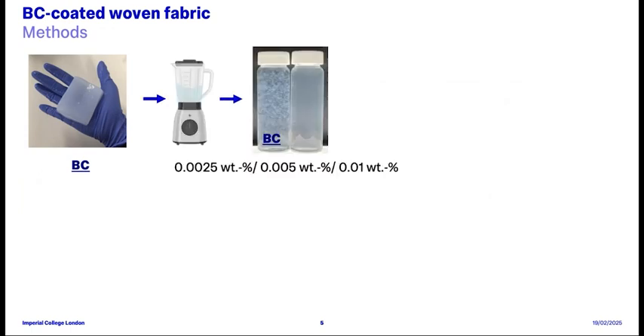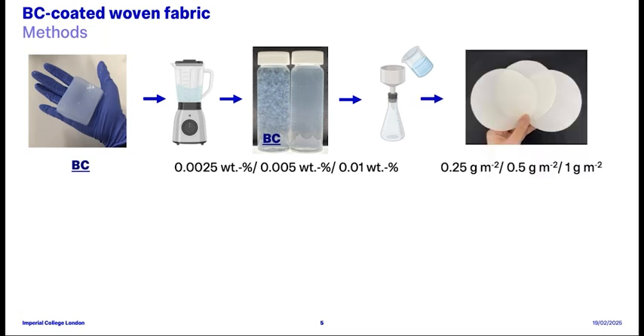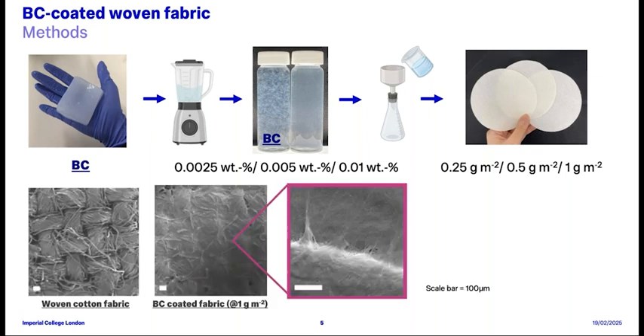For coating, here we're adopting a simple procedure where the bacterial cellulose pellicles are first blended in water and the bacterial cellulose suspension is then vacuum filtered onto a woven fabric substrate to obtain a bacterial cellulose coating of 3 different grammages, with the highest coating grammage of only 1 gram per square meter. These samples are then oven dried at 120 degrees for 30 minutes. From these SEM images, we can observe that a nonwoven bacterial cellulose coating is deposited on the fabric surface, closing the inter-yarn pores of the fabric substrate.